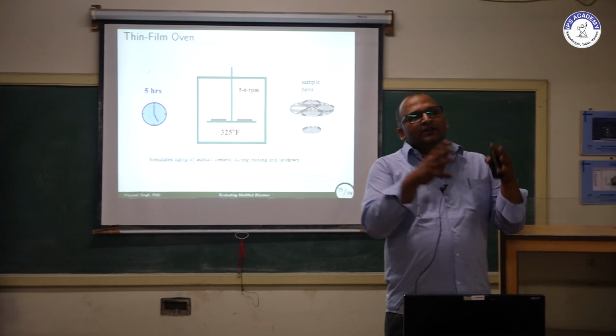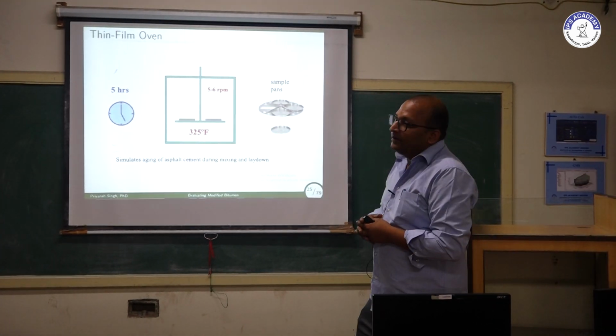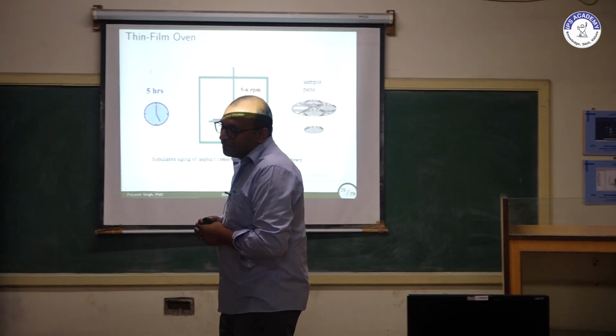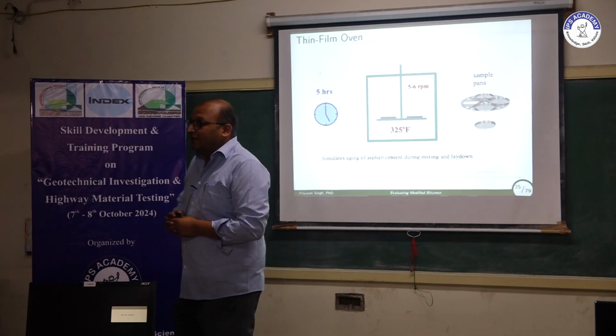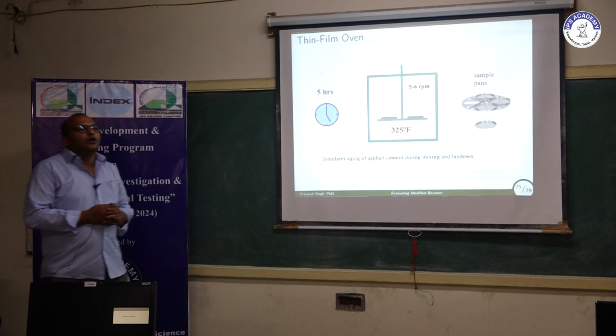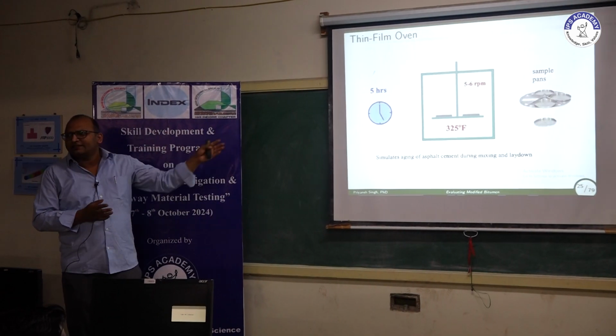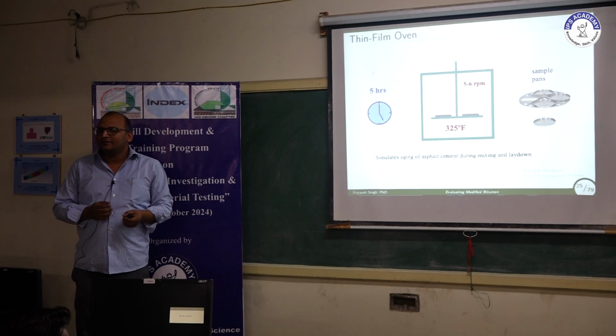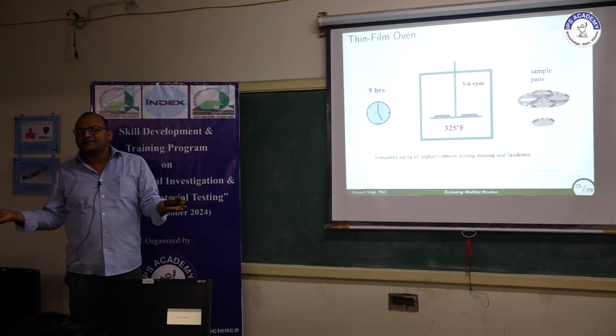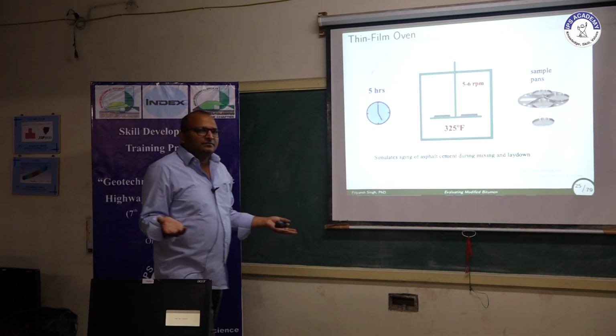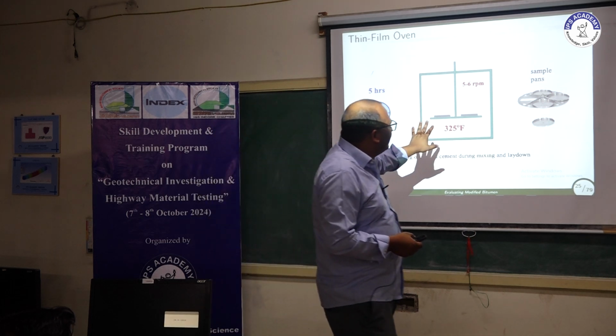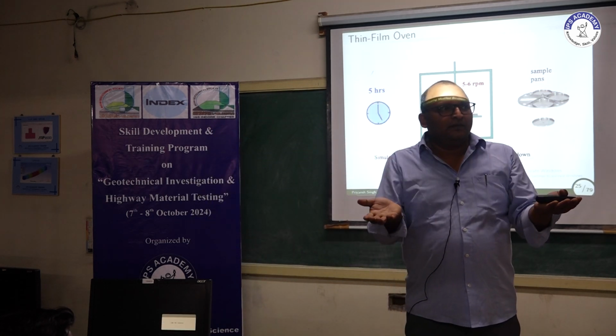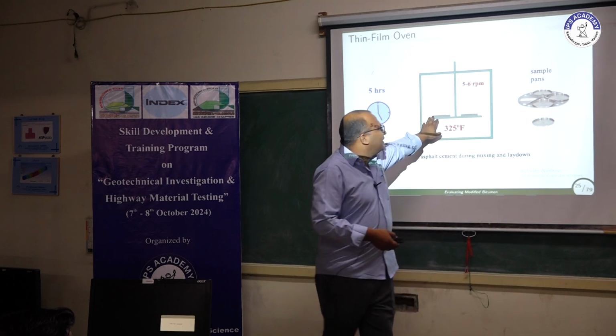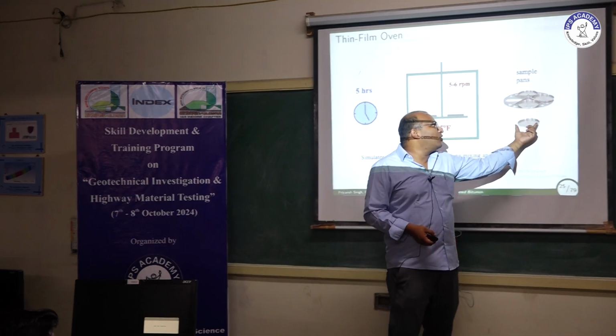So in order to simulate short term aging, there are two protocols: thin film oven testing and rolling thin film oven testing. Have you done this test? You might not have performed this test. This is a simple oven. There is a horizontal plate, you can see here, and then we have some small plates.